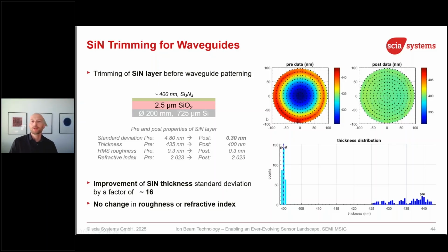So we did this ion beam trimming process on a 200 millimeter wafer with silicon nitride. You see it here on those graphs very nicely. It's going to be very uniform. But maybe even more impressive on the histogram here, where we see the thickness distribution. Before, maybe we have like 20 nanometer variation, and after plus minus 1 nanometer. Very impressive. The theoretical resolution is basically one atom, it's an atomic process. What we can get in reality depends a lot on the measurement accuracy, not too much on the tool. Also important, there's no change in roughness, there's no change in refractive index. So we keep the same material properties, just argon ion beam etching and removing some nanometers on top.